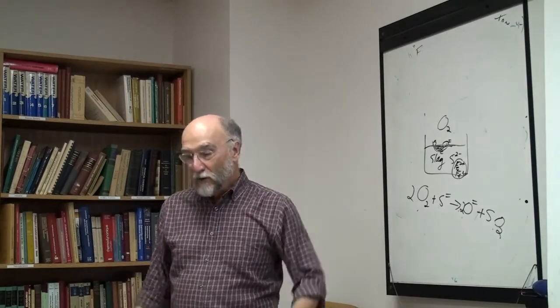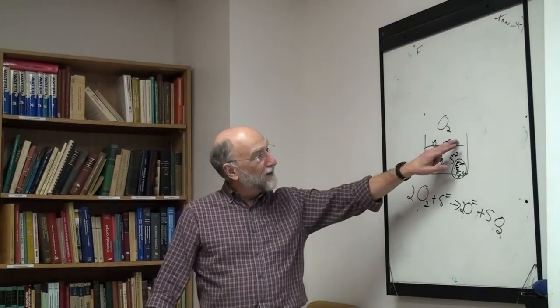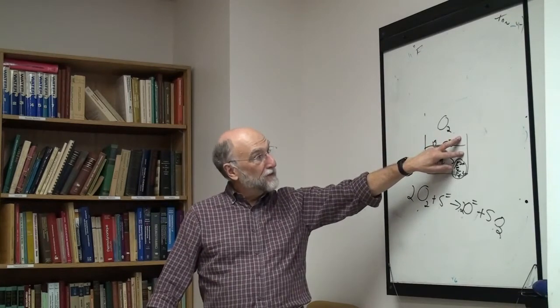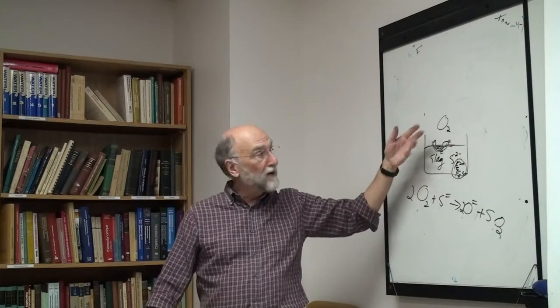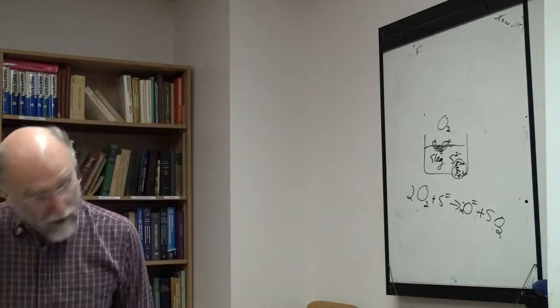As long as you keep the oxygen pressure quite high, blow air. The oxygen pressure in air is about 0.21, so that's enough to form the sulfate. But if there's a reaction going on and the oxygen becomes depleted at the surface, you're going to speed it up. So just keep your air flowing over the surface, and that'll slow down the SO2 production. It seems kind of counterintuitive. Anyway, this is the electronic nature of ionic materials, and that applies to the solid and the liquid ionic salts.